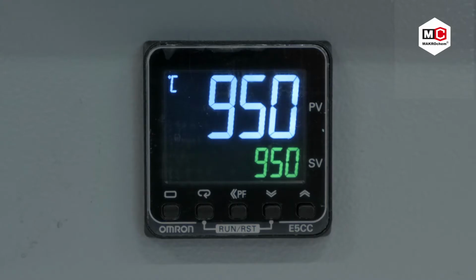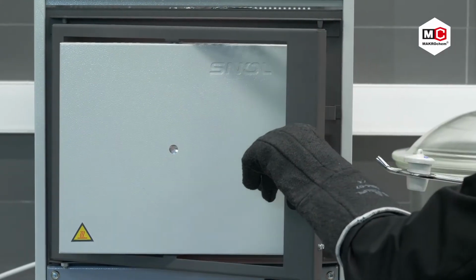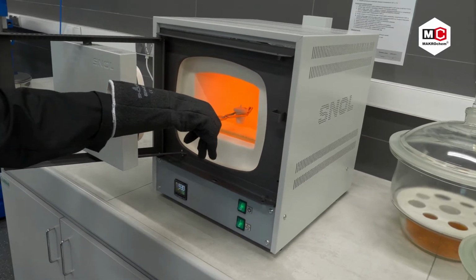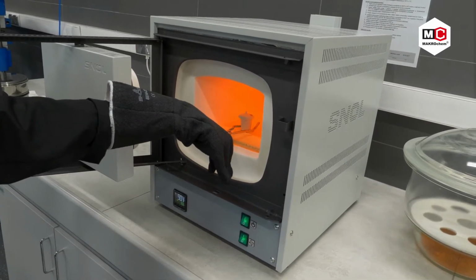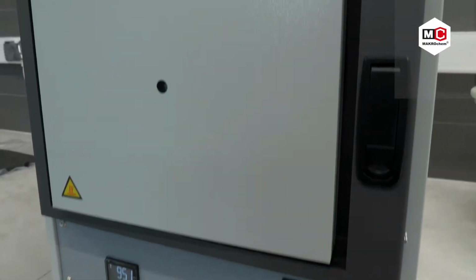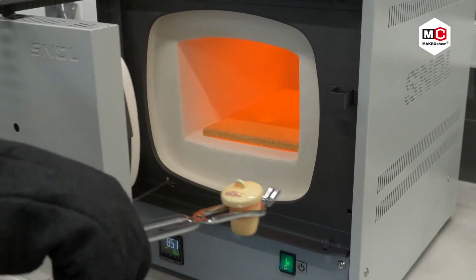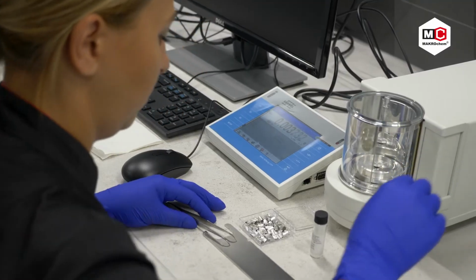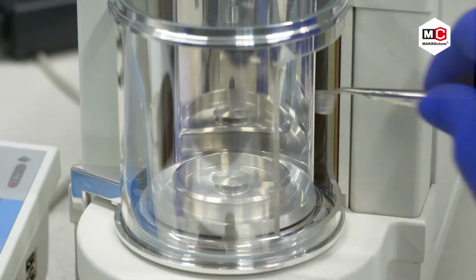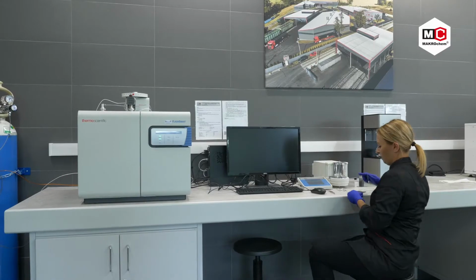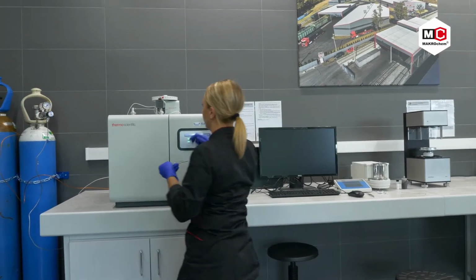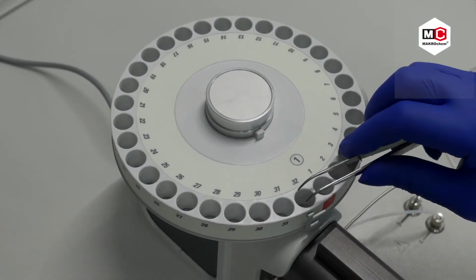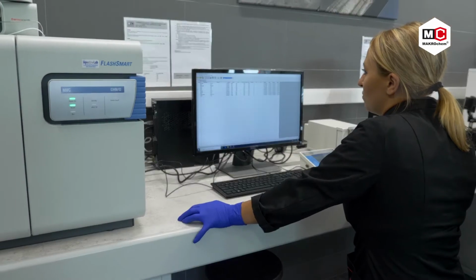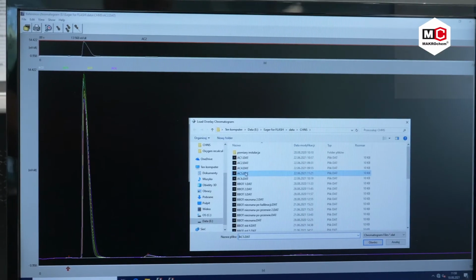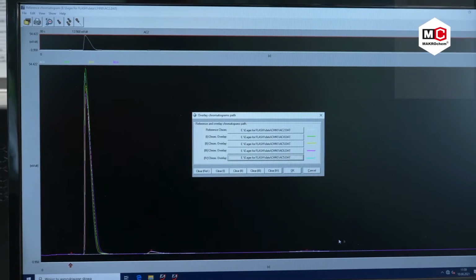Especially in the case of recovered carbon black, volatile content and ash content are of extreme importance. If those values are too high, the allowed limit of polycyclic aromatic hydrocarbons in the compound will be exceeded and the characteristics will deteriorate. We perform more detailed analysis of composition of carbon blacks with measurement of elemental content such as carbon, hydrogen, nitrogen, sulfur and oxygen. In this method, we burn the sample and analyze the resulting oxides.